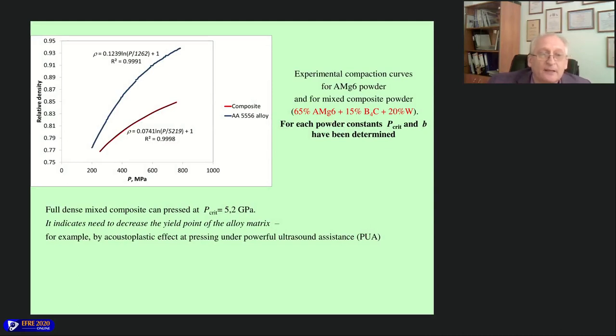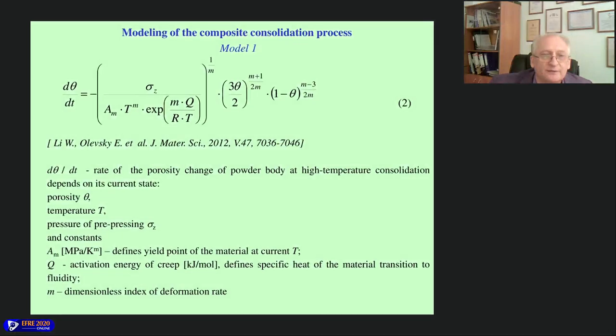Here you can see the plots of the densification of such composite powder, and for each powder we calculated the constant for the mentioned logarithmic equation of densification. A fully dense mixed composite can be pressed at a very high critical pressure, around 5 gigapascal, without sintering, without temperature treatment. But if we also apply temperature during pressing by the spark plasma sintering technique, we can achieve full density with pressing around 100 megapascal.